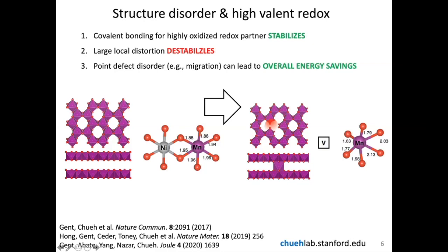But on the right, if I move one of the transition metals from the metal layer to the lithium layer, this actually opens up a vacancy in the transition metal layer. And this allows the strain energy to be accommodated. On the right, you can see the density functional theory calculation. The bond between the metal and the oxygen shortens dramatically. But because there's a metal vacancy created by the metal moving out of the transition metal layer, the strain energy can be accommodated. So when you compare the left to the right, although you have paid the penalty of forming a defect pair, that is the transition metal vacancy and the lithium antisite, the overall energy is more stable because you're allowing the strain to be accommodated.